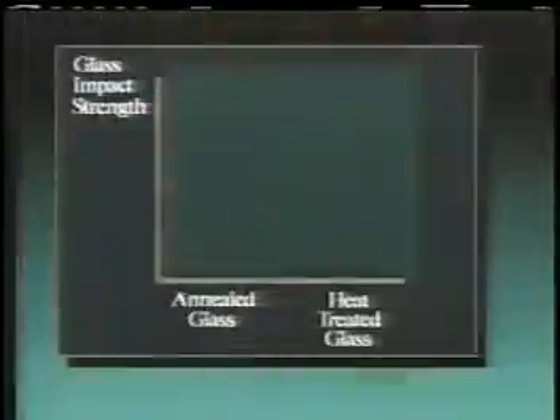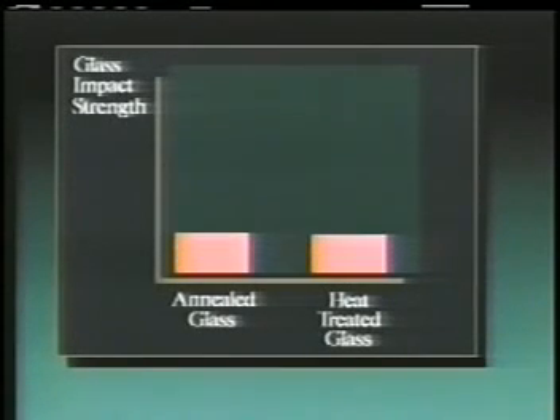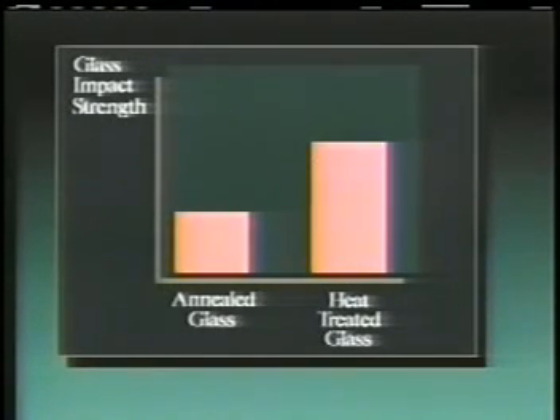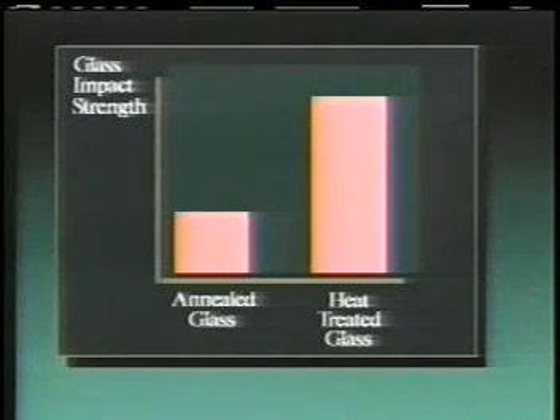The areas around the rim are reheated to nearly the softening point and then rapidly quenched with air to set up preferential stresses. The strength increases from heat treatment range 3 to 4 times over annealed or untreated glass. This graph shows the impact strength difference between a heat-treated glass and the same glass in an annealed state. You see that the glass with the heat-treated rim area is able to withstand significantly more abuse.